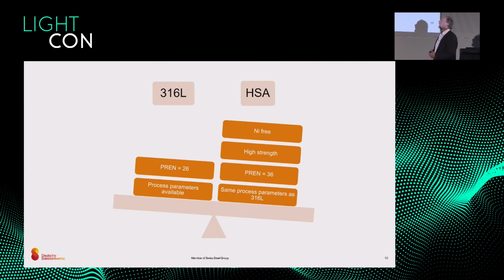If we compare the two grades, the HSA is nickel without nickel. It has a higher strength. The PREN number is something like the corrosion resistance. It's a chromium equivalent. And the big advantage of the 316L, everybody who delivers printers has process parameters for this grade. And the HSL can be processed with the same process parameters as the 316L. You change nothing, you can print it with the same parameters, just change the powder.